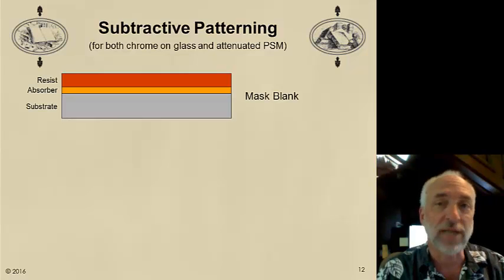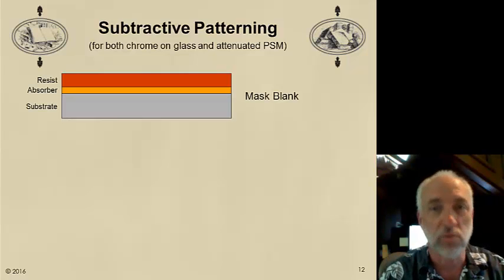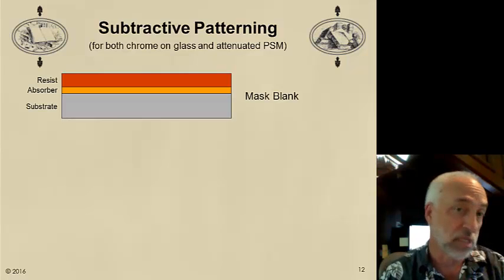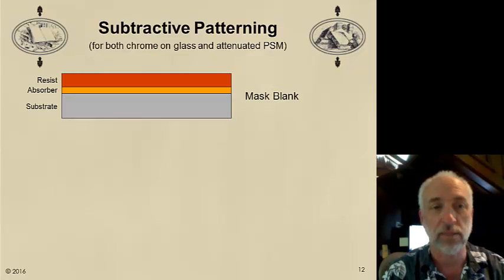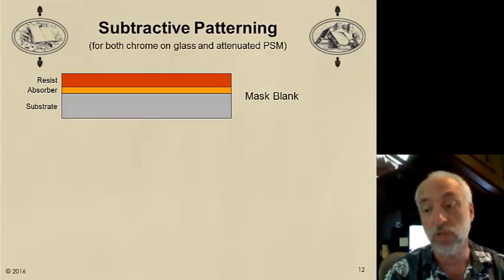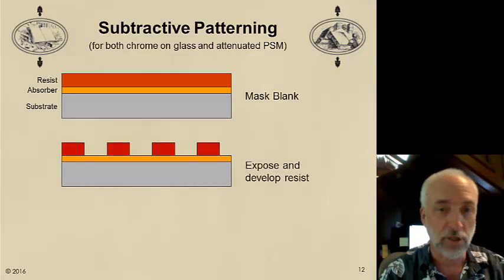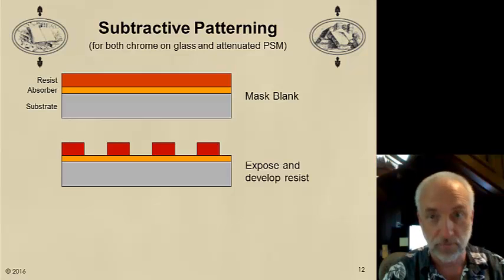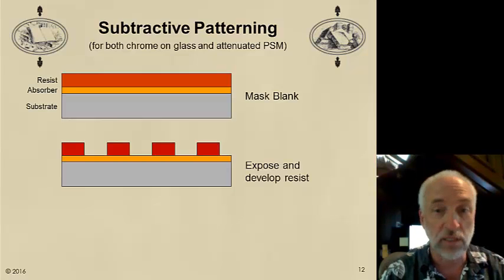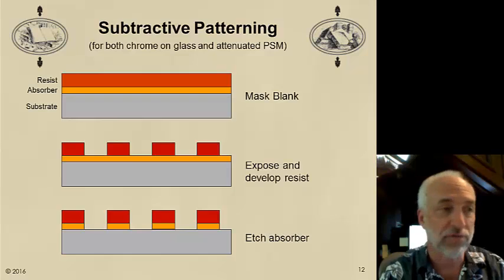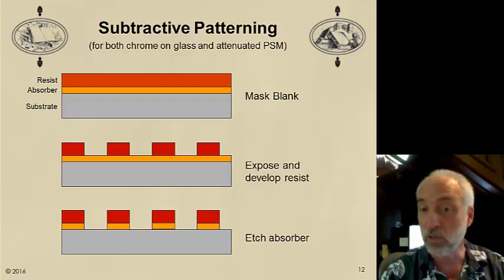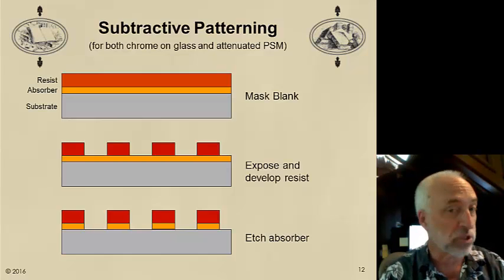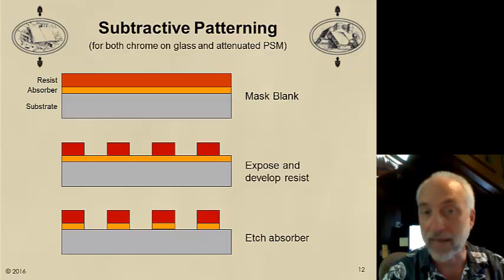So in the subtractive patterning, chrome-on-glass mask, attenuated PSM mask, we begin with the mask blank. We have resist coated on an absorber, coated on our quartz or glass substrate. Then we do our lithography. We're going to talk about the writing step in the next lecture. We expose and develop the photoresist. With this, the resist is an etch mask for an etching. In the old days of larger feature sizes, we would use a wet etch for the chrome, but with smaller feature sizes and with attenuated PSM, we will etch the absorber with a plasma etch process. Once we strip the photoresist away, we now have the patterns that we're looking for.